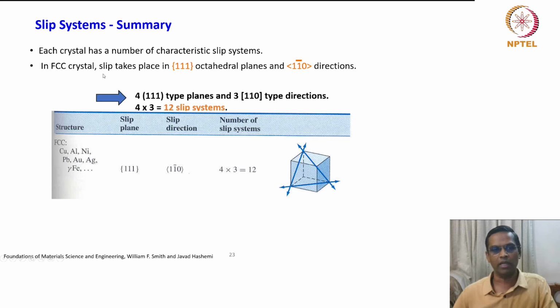For example, in FCC we have already seen that slip takes place in 111 type octahedral planes and 1 bar 10 directions. We have 4 types of 111 planes and 3 110 directions, which is shown here in this schematic, and 4 into 3 is 12 slip systems. Examples are copper, nickel, aluminum, lead, gold, silver, gamma iron, and so on. They all belong to this kind of crystal system.